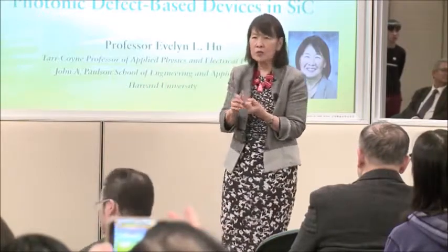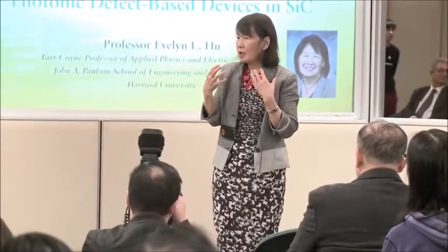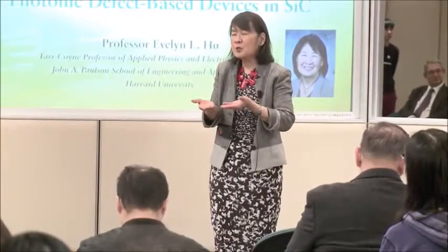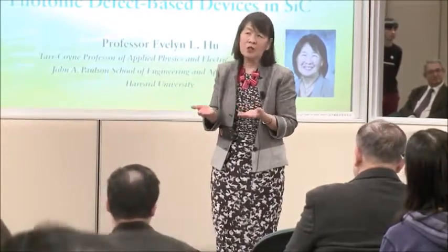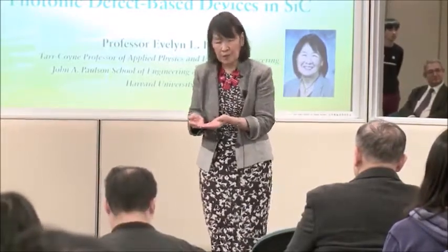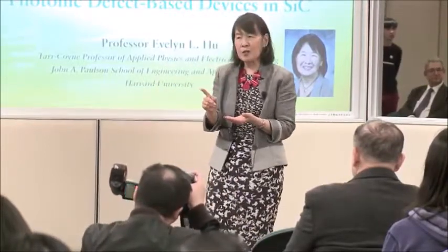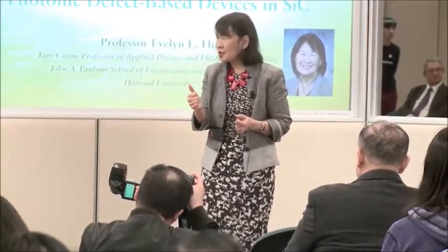We tried, and actually people have looked at this for diamonds as well. We thought maybe if we do an electron irradiation, the residual damage will be less. Turns out, and maybe just because of our sensitivity, we don't see much difference between ion bombarded samples and electron bombarded samples. I will say, unusually though, we have had some experience where even when we ion bombard, we don't do an anneal, and the results are almost as if you didn't need an anneal.